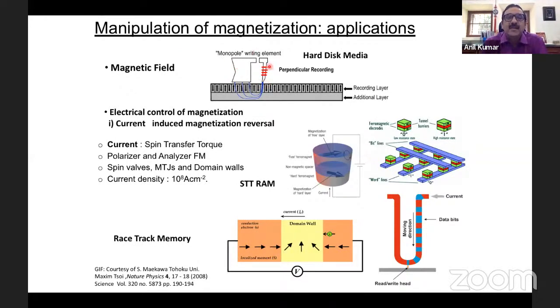You have a yoke where there is a wire wound around this. And if you apply plus I current, it creates a magnetic field. And this is a broader one to close the flux. And locally, you can apply a magnetic field which is higher than the coercivity of this material. If I apply plus I current, plus H field, magnetization is upward. And if I apply minus I current, minus H field, the magnetization is reversed. So you can switch the magnetization up and down.